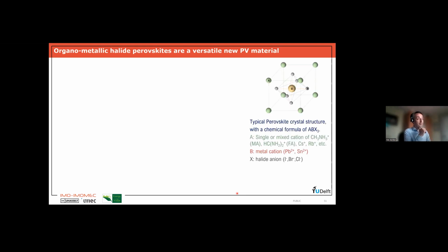So these perovskite materials are a kind of hybrid organic-inorganic material that has become very popular in PV because, in a very short time after the discovery of this material, we have been able to make very highly efficient solar cells with it. We call it a perovskite material because it has a typical perovskite structure. There are many materials that have a perovskite structure. The perovskite structure is typically a cubic lattice, as is shown here, and you typically have a chemical formula of ABX3.